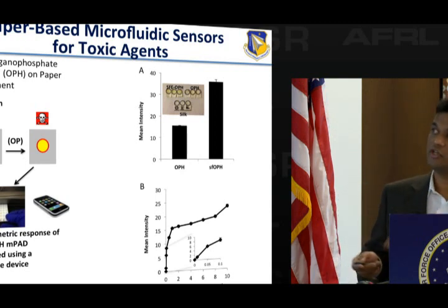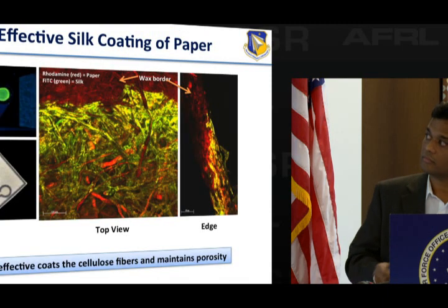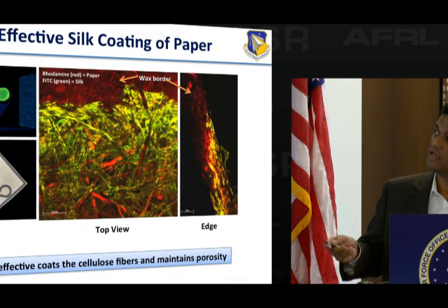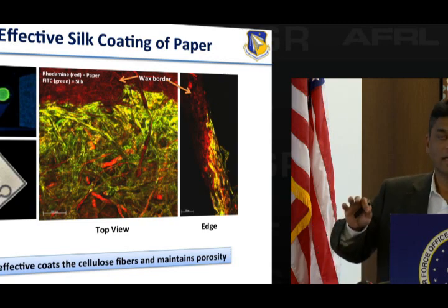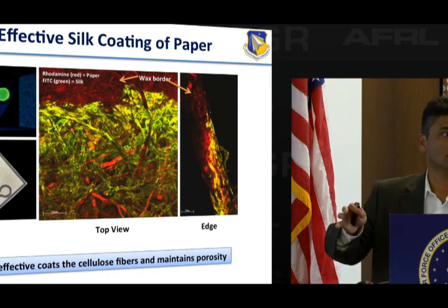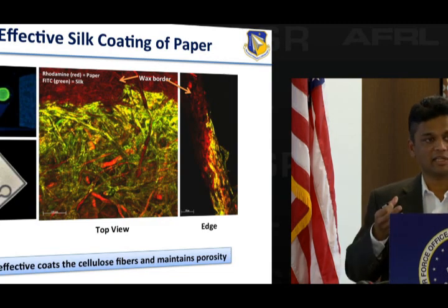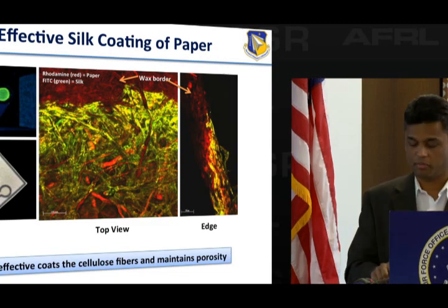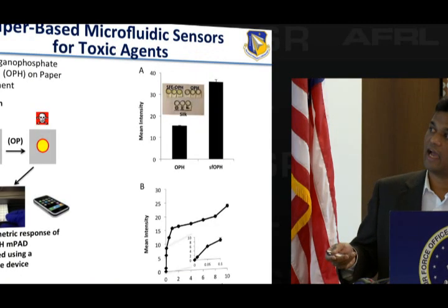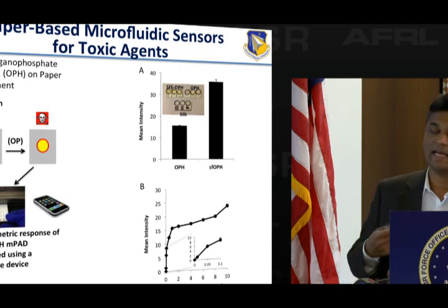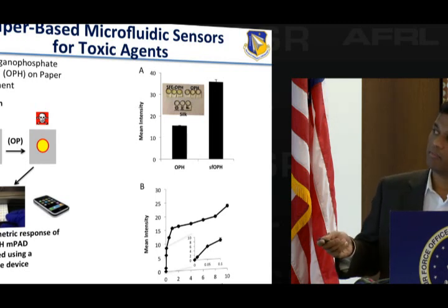What we showed is you can use the silk fibroin to actually coat paper. So this is just fluorescent imaging showing that the cellulose fibers can be coated with silk fibroin. And I can throw in an enzyme as well, so it'll encapsulate the enzyme, and it'll immobilize it onto the paper. And then if I add OP, which is organophosphate, so organophosphate hydrolase is the enzyme that's used for detecting nerve agents and also for decon. What happens in the presence of organophosphate, it turns yellow.